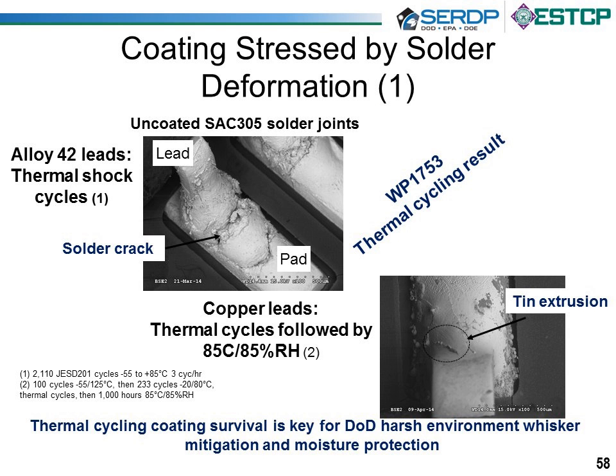We take a look at what a coating needs to live through in a traditional DoD assembly. And one of the first things we saw, this is from our 1753 project, we saw a lot of deformation of our solder joints. So this first set here was alloy 42 uncoated in a thermal shock cycle. That thermal shock cycle is the industry standard for piece part testing. It's a 3-cycle per hour, very rapid thermal transients, but it really made a lot of damage on the solder joints, and it also led to suboptimal whisker growth. We ended up with a lot of deformation mechanisms that didn't have anything to do with whiskers. They would stress a coating a lot, so we're paying attention to that.